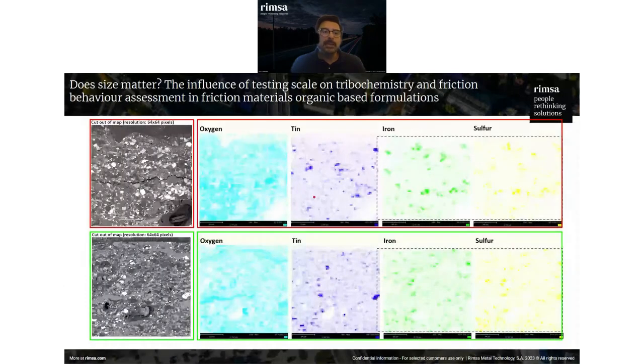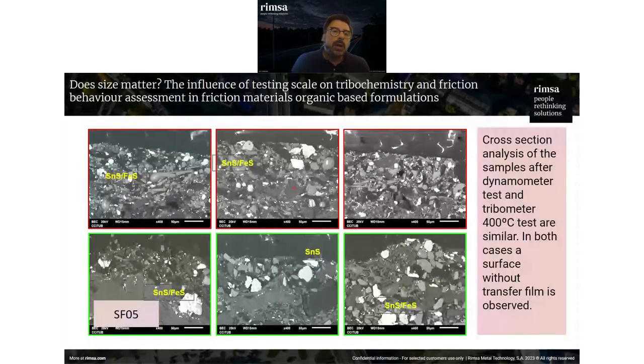And if we go to analyze the elemental map distribution on the surface after the dynamometer or the tribometer, we see here that there is no oxidation, neither on the iron sulfide nor on the tin sulfide, on either the dynamometer or the tribometer. And if we analyze this with a SEM, we are going to find that the particles of the sulfides are still giving the signal of tin sulfide and iron sulfide, both in the cross section after the full scale dyno or the tribometer.